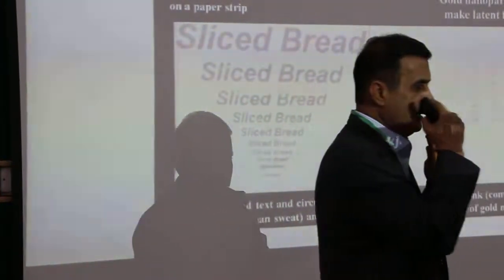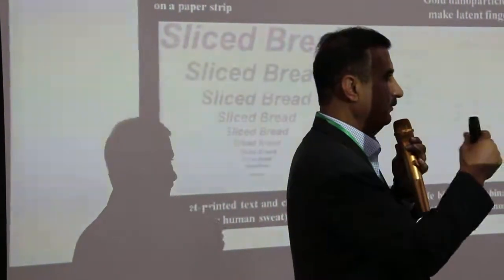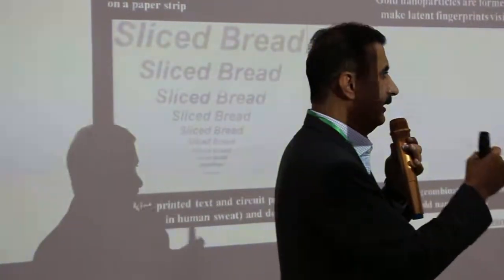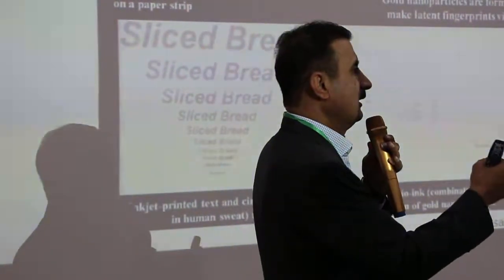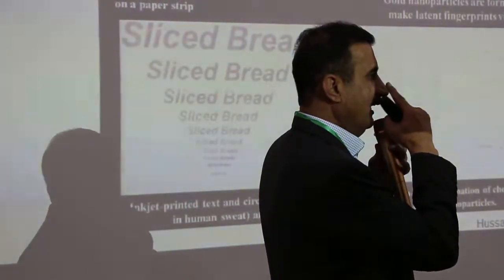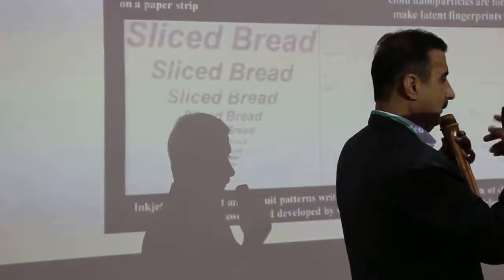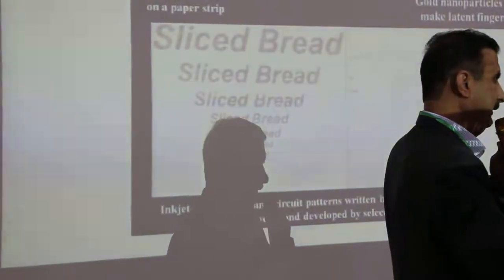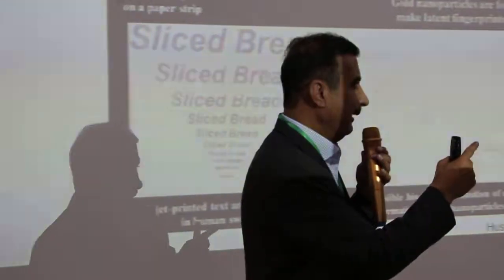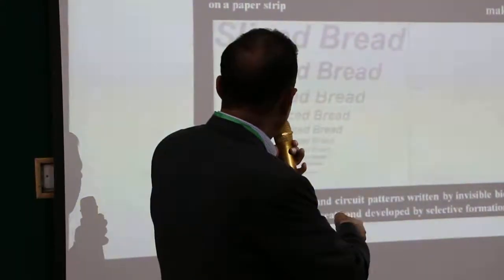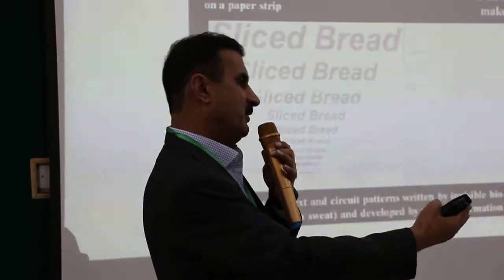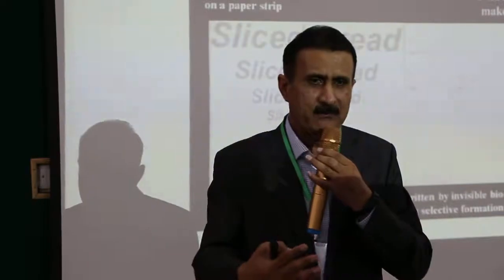Because it had just mixed up so many things, we tried to figure out exactly which chemical is responsible for the conversion of gold ions to gold nanoparticles. We found that it is a biosurfactant, which is very abundant in our body. We then made bio-ink using that biosurfactant to print text patterns and circuit patterns on different substrates like plastic and other materials.